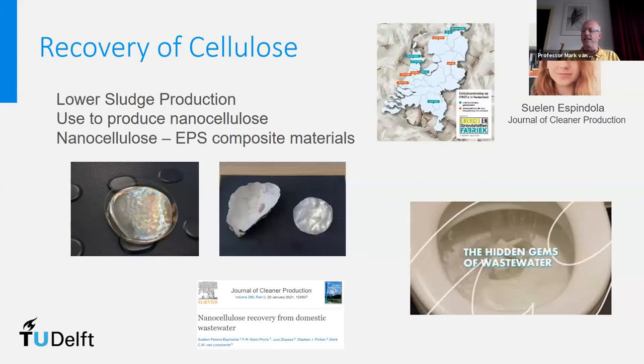And it's very easy with a sieve to recover from the incoming water or from the sludge. So it's a very simple step to recover it. And again, the recovery costs are almost the same as the sludge disposal cost in the Netherlands. So that's why in about 7 or 8 wastewater treatment plants in the Netherlands, the cellulose is currently recovered. Now, cellulose itself is, of course, you can just use that for any other option as where you normally use cellulose.